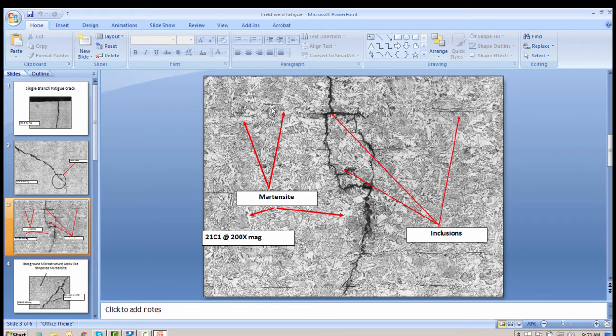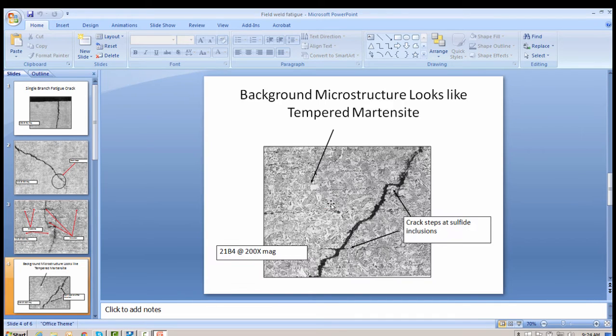And also what you see here is martensite. Now this background martensite tells me it was never heat treated. We'll start with that. The only way you can have this martensite on the surface of the weld is in the crystalline structure during the welding process. You go from what is known as body center cubic to face center cubic. Now what happens is the carbon atoms in the center of the crystal, the metallurgical center, are migrating from the center of the crystal to the surface of the crystal. And when they settle on the surface like that, they form martensite. Martensite is very, very hard. And this is a good picture of the tempered martensite, where it has gone from body center cubic to face center cubic. Okay, so fatigue is verified.